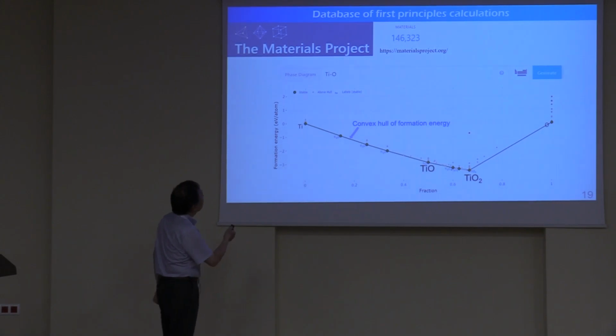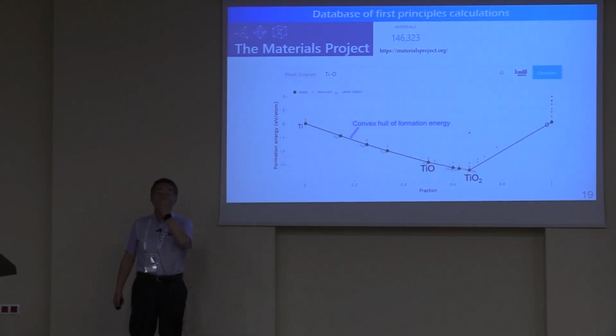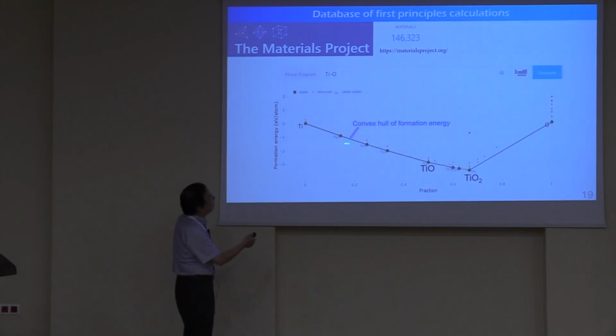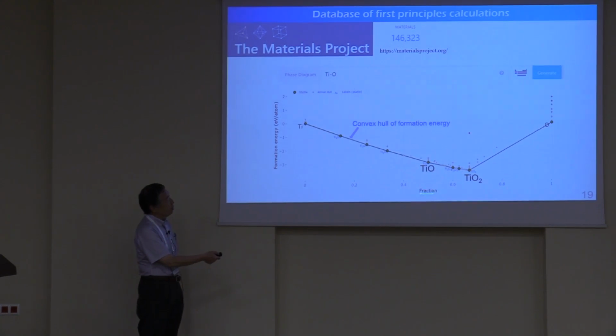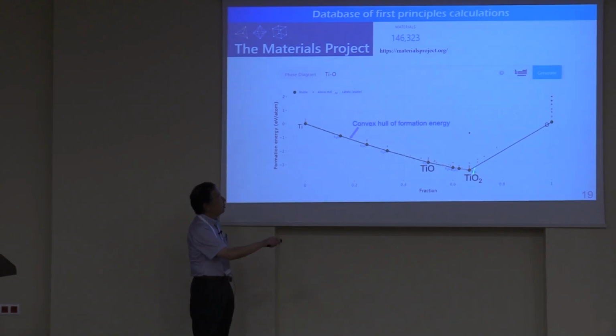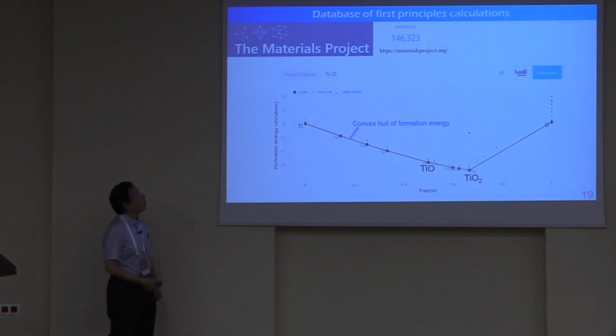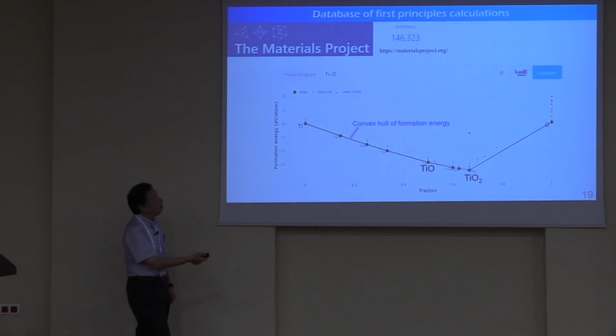For example, if you type TiO and click the phase diagram, you can immediately produce this type of diagram, which shows the convex hull of the formation of the titanium oxygen system. The horizontal axis is a fraction from 0 to 1. So here is TiO2 because the fraction is 0.66. This is TiO, so the fraction is 0.5. Here is titanium metal, here is O2 as a standard state.